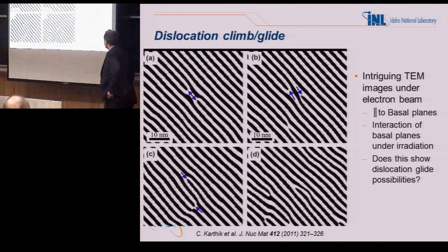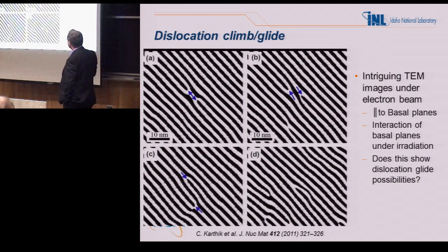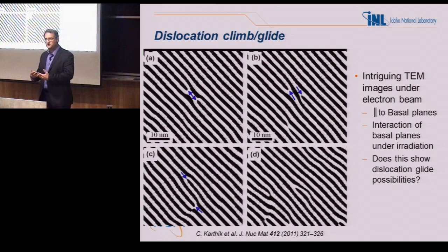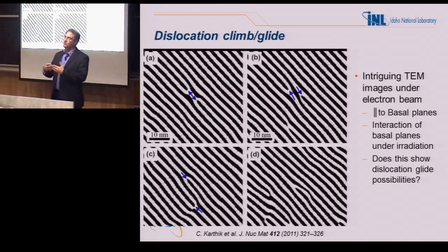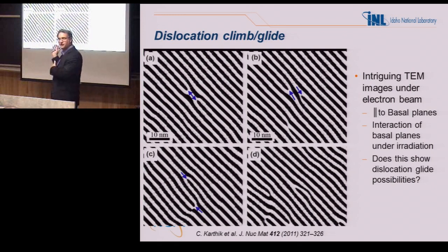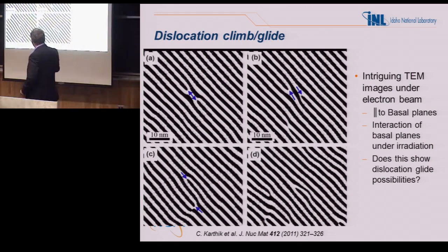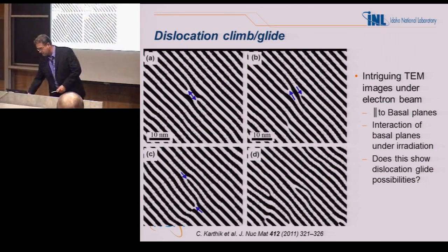Well, guess what? Some recent work out of Boise State shows that under at least TEM and the electron beam there, you do start to see some kind of interaction between the basal planes. Well, the model doesn't show that, but reality says it is. So as I said, folks, those of you who rely upon the textbooks, that they know what they're talking about, don't fool yourselves. It's written by us fools on the front line, and we get it wrong almost always the first time. We need to go back in. That's what science is all about, going back in and revising all of the assumptions.